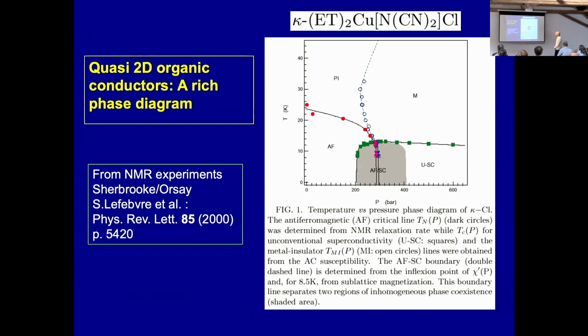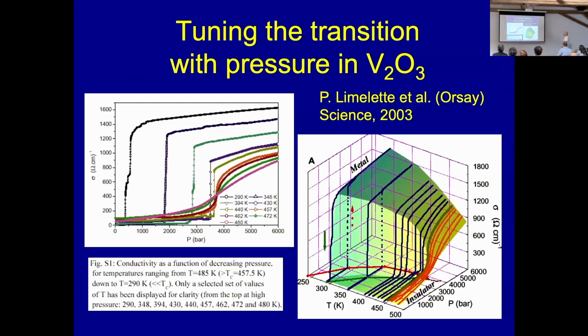And in the kappa-ET salts, there is an even more interesting phase diagram. Again, these two phases, a first-order Mott transition, and a critical endpoint. I'm talking about the vicinity of this point. But now at low T for this material, we have again ordering, but we also have superconductivity at about 14 Kelvin. So in V2O3, what Patrice Limelette did in the old days is to measure conductivity versus pressure.